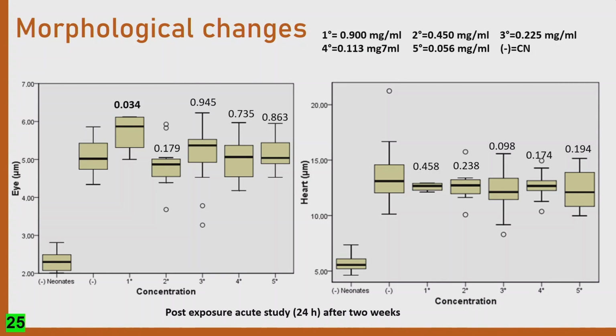Talking about some morphological changes, we can analyze the body, the heart, the spine, and the antenna of this Daphnia magna, and we can check whether these nanoparticles are causing significant changes, statistically speaking. So after 24 hours of exposure, we can see that this nanoparticle has no significant influence, based on the P value not being more than 5% here. We have one concentration where it is smaller than 0.05, but it's not significant enough to say that, with the value of only one concentration.